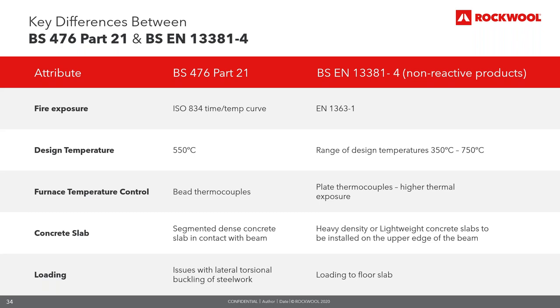The design temperature. A commonly held assumption was that 550 was the highest limiting temperature that a steel structure could withstand before collapse. Research has shown, however, that the limiting temperature of a structural steel member is not fixed at 550, but will vary according to two factors: the temperature profile and the load. BS EN standards allow for a range of design temperature data to be collected to support structural modelling of steel sections in order to calculate specific limiting temperatures for each individual structural element that is used.